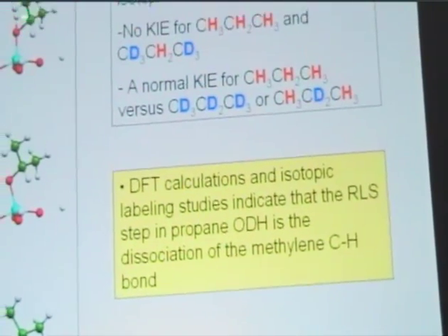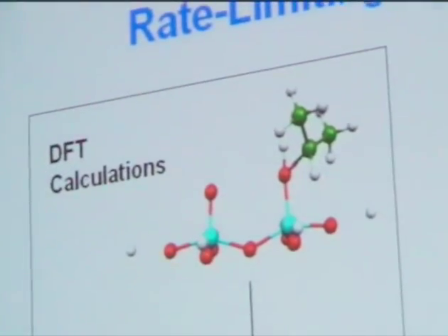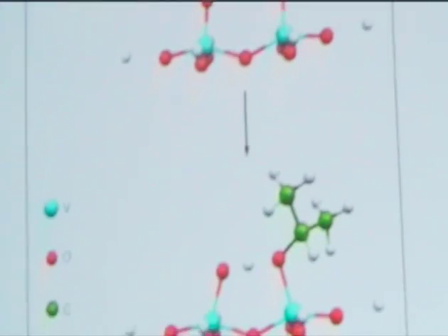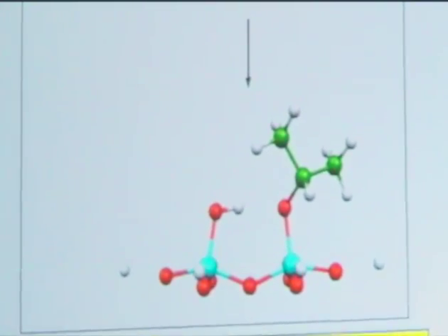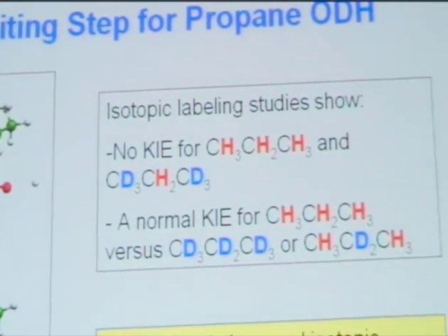And what we find is that, as one might expect, the weakest bond is the CH in the methylene unit. It transfers first to the vanadyl, then across the gap here, and eventually that proton ends up on a second vanadyl, and what we have here is an isopropyl oxide group attached to vanadium. And that it is the CH bond of the